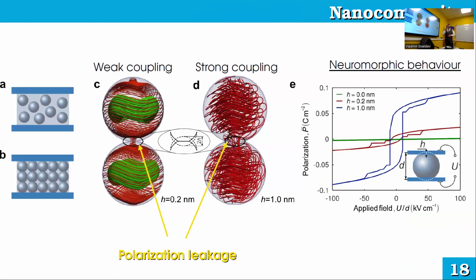Yes, and I told you that I will tell you something about applications of this. So here we consider nanocomposites of such particles. For example, we have two nanoparticles, but we have periodic boundary conditions, so we can put three of them, four of them, more. And two nanoparticles touch each other with different sizes of spots. Here is a small spot, here is a bigger spot, here are the actual values. What is interesting is that even with a small spot, we have polarization leakage from one particle to another. But the volumetric tori still persist. And with a bigger size of this spot, we have pretty different behavior. We have strong coupling between these particles, and basically no tori between them.